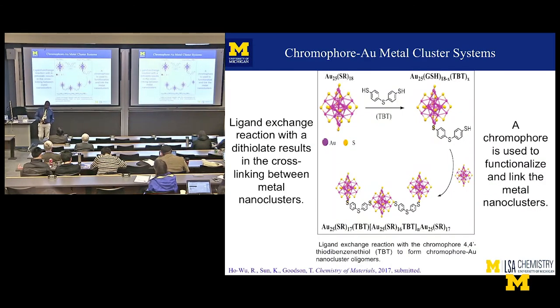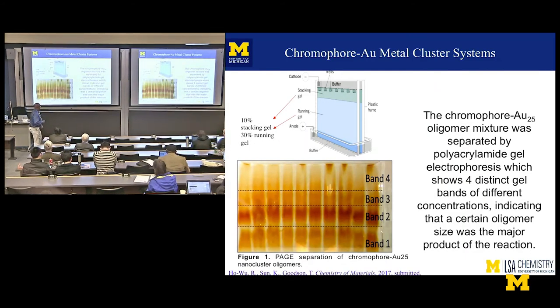So she had to figure out a way to attach these metal clusters together. And here's a gold 25, and here's this TBT small chromophore, which we could later make a big chromophore with, but proof of concept first. Then you attach the TBT, and then you can do this ligand exchange reaction, and then you can make these oligomers. We learned from our biochemist how to use this PAGE gel electrophoresis technique to separate these structures. And you separate them based on the bands, and of course the bands that fall to the bottom, if you've used PAGE before, are the lightest, and the ones that stay at the top are the heaviest, I think.